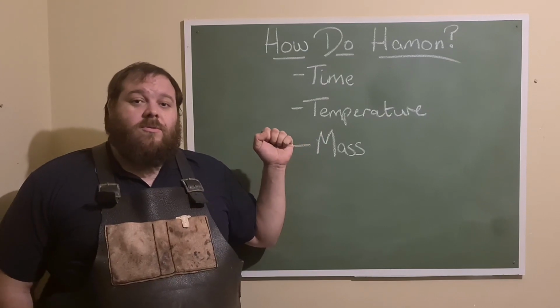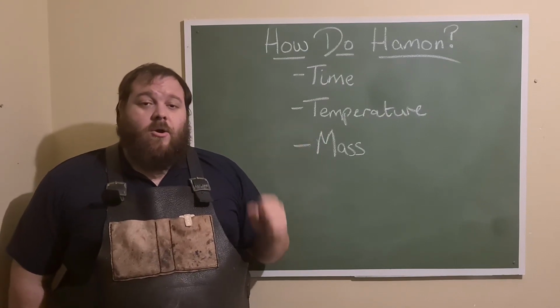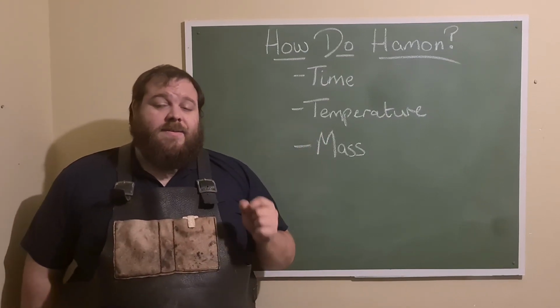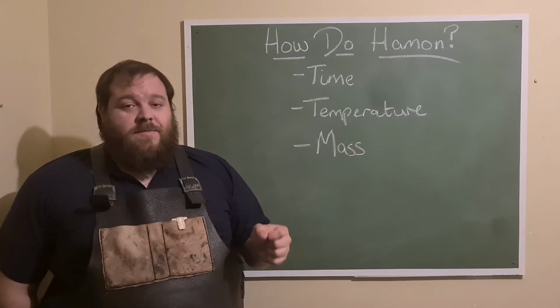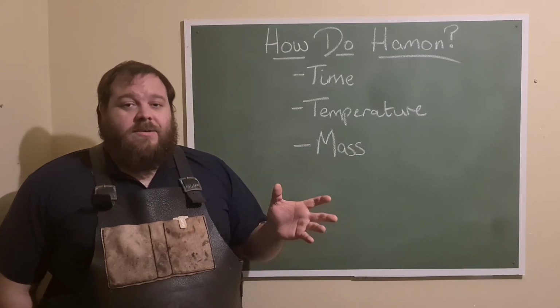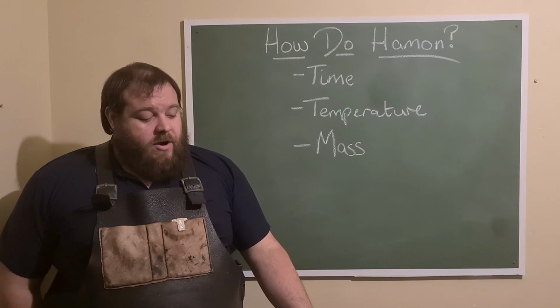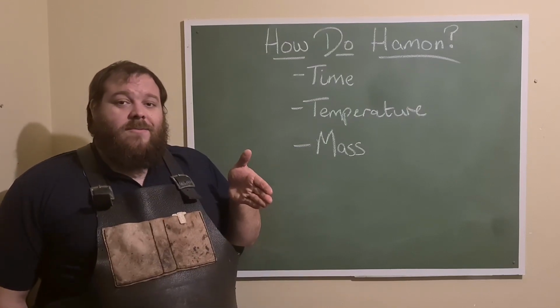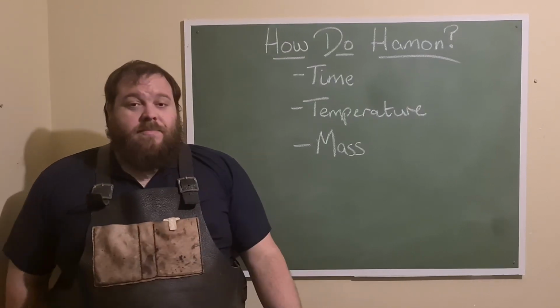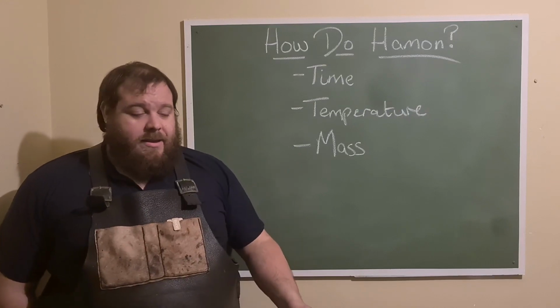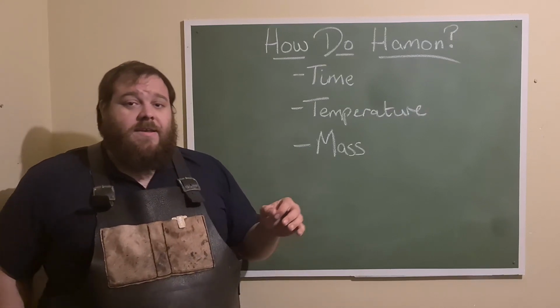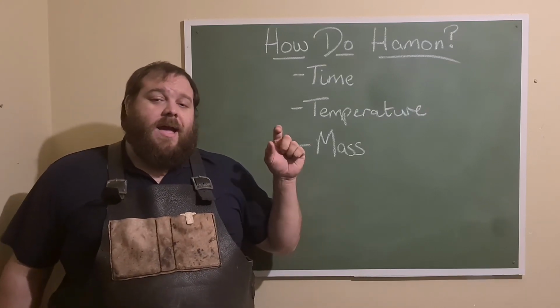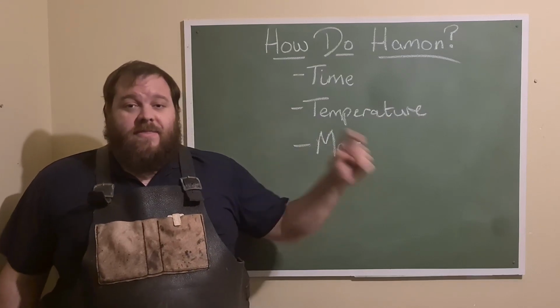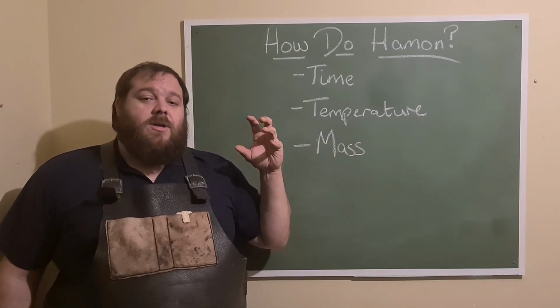You can do that through the means of an interrupted quench, and that only works if you have sufficient mass in the spine. The means by which you do that is to heat the whole blade critical, quench it into your quenchant very quickly, pull it out while it's still glowing, and then push it back in and out again and out and in again. And the reason you do that is because you're trying to slow the speed at which the large mass, the thicker area of the spine, cools down.